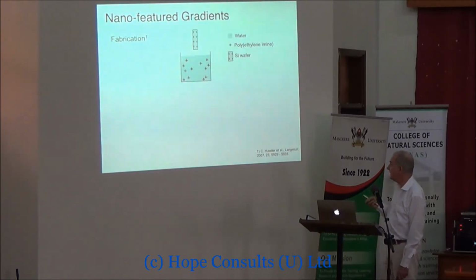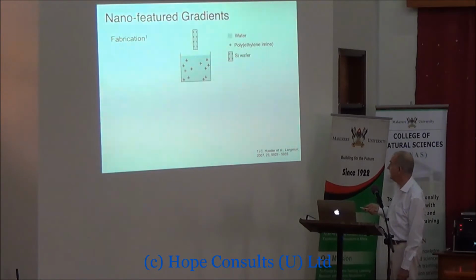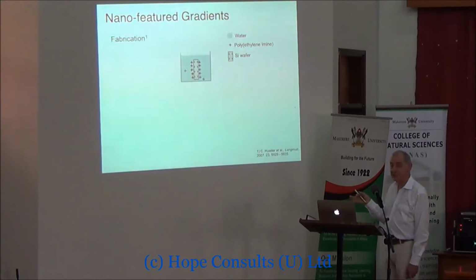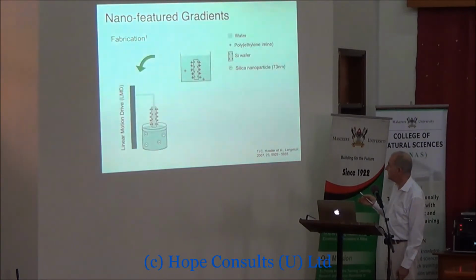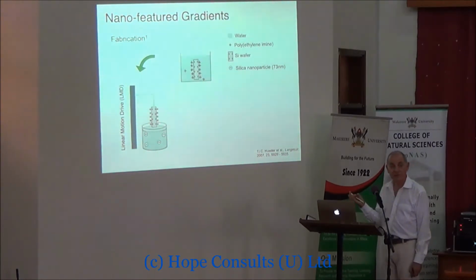And so we made, and you can't use sandblasting to make things rough on the nanometer scale. If you have nanoparticles, they have no momentum, so they're not going to do anything to an aluminum surface. So we have to use a completely different technique. We used a silicon wafer as our base, and then we took a polymer which has a positive charge, polyethylenimine, and we dipped our wafer into it. And the reason we did that is we wanted to have a positively charged surface, so that we could then dip it into a suspension of silica nanoparticles that would stick electrostatically onto this positively charged surface.